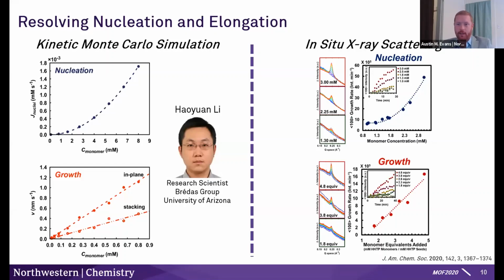This inspired us to develop some experiments at Argonne National Lab using synchrotron diffraction to look at the rates of SAXS features coming in, which is a bit more challenging to interpret quickly on a slide, so I've omitted that. But by comparing the SAXS data to the wide angle scattering, where you can see Bragg diffraction peaks, you can determine what the growth rate is of that 100 peak in relation to the SAXS data. Taking those two things together, we find that if we double the monomer concentration, the rate more than doubles. We see a nonlinear dependence. That's in contrast to the situation where we included pre-existing seeds and doubled the monomer concentration: in that case, the growth seems to be first order, so if you double the concentration, the rate doubles.